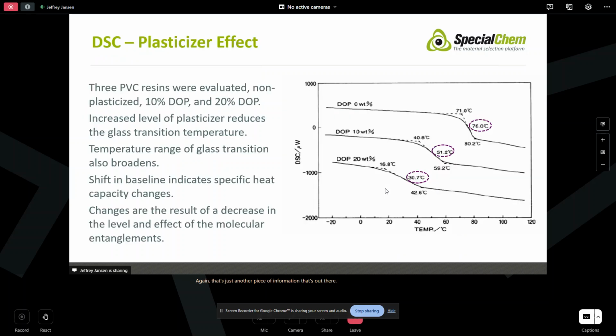DSC can be used to look at the plasticizer effect. So here we have an example of some polyvinyl chloride, some PVC resin. We have some that's not plasticized, some at 10% dioctyl phthalate, and some at 20% dioctyl phthalate. So plasticizer changes the physical properties of that PVC. It takes the PVC in a non-plasticized state, something like a rigid PVC pipe, and once we add plasticizer to it, turns it into something more like a power cord. It's very, very flexible.